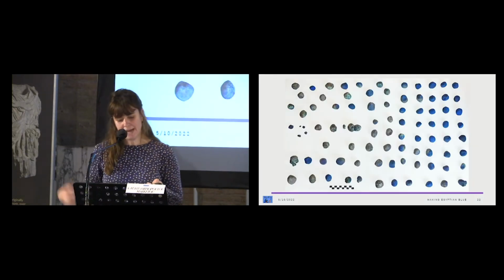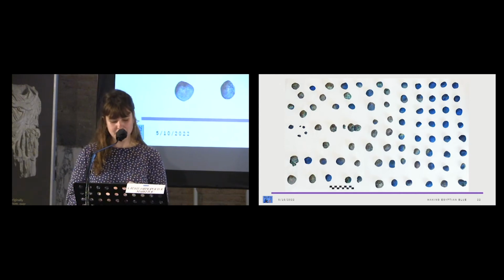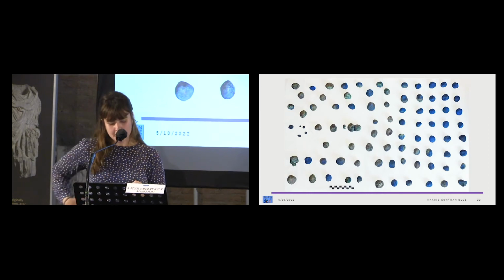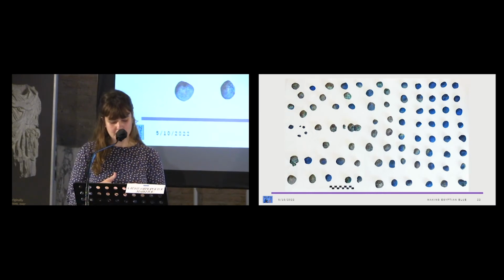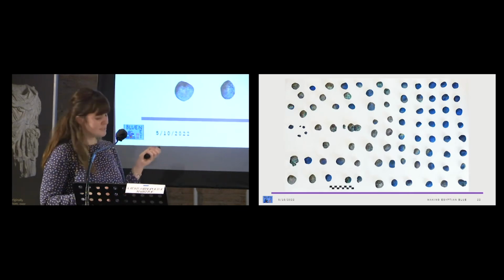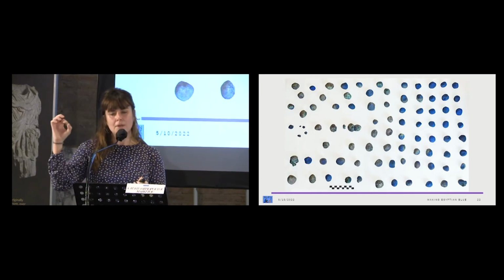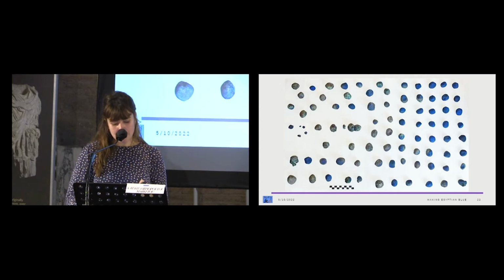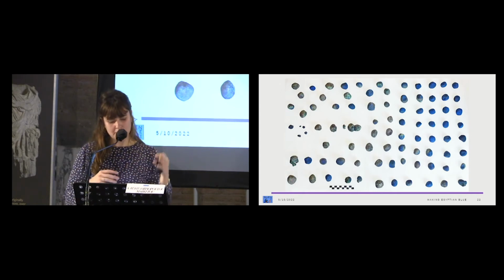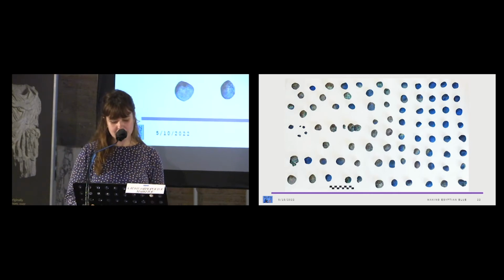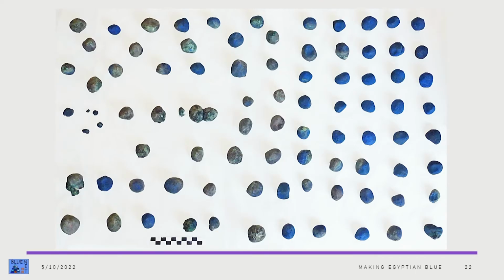The ceramic vessels, the saggars, in which Egyptian blue pellets were placed during firing, according to Vitruvius's description, have been considered in general a very important factor in the production of Egyptian blue. However, no saggars have been found in the Kos workshop context, at least so far, and the finds that, as you can see, stand alone as individual pellets of about 3 centimeters across, as opposed to the lumped pellets from Memphis or other sites, and the cakes from earlier productions, suggests that the firing of the initially shaped paste of materials was carried out on a flat surface and not on a small saggar.